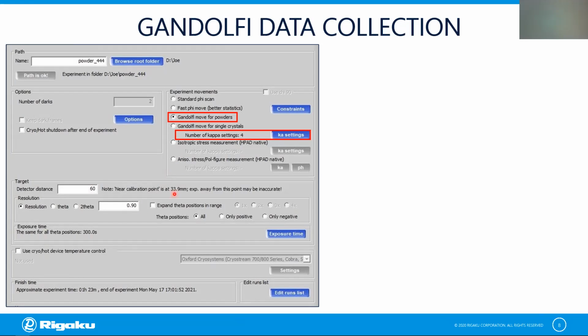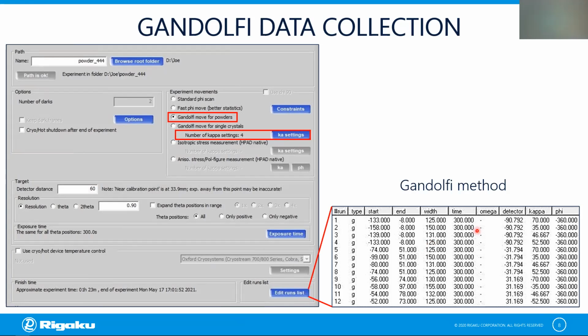And using all these settings, CrysAlisPro automatically calculates a strategy, so you will collect data across a given resolution range, basically. And you can access the strategy via this run list button. And when I do that, here is what I see. First, CrysAlisPro has set up two different detector positions to collect the high resolution data, and then another detector position to collect the low to medium resolution data. And it does that on each side of the beam, therefore the negative angles first and then the positive angles.